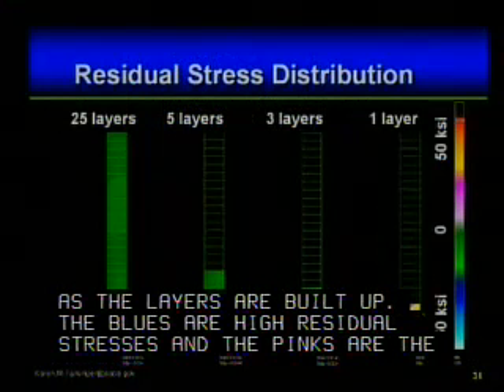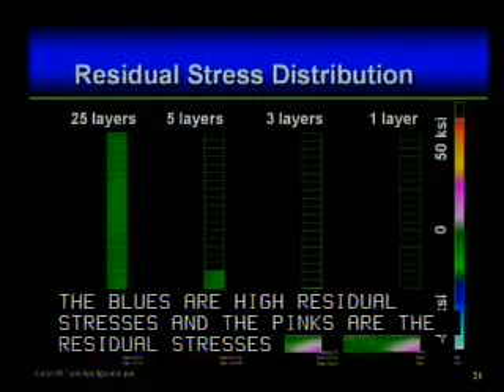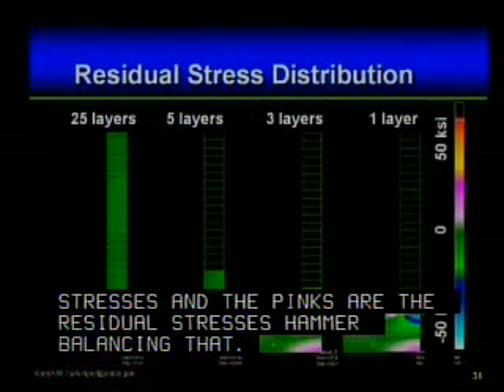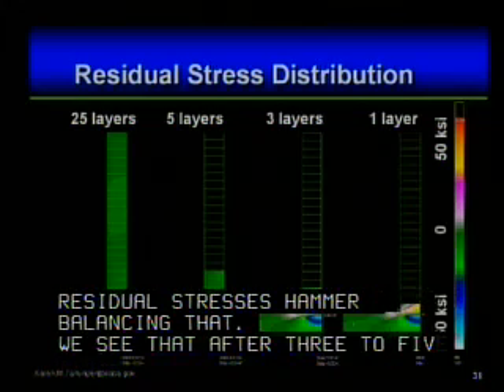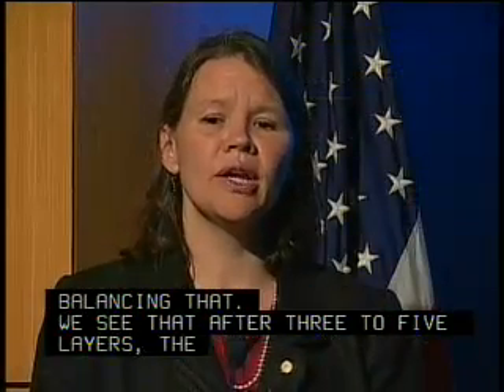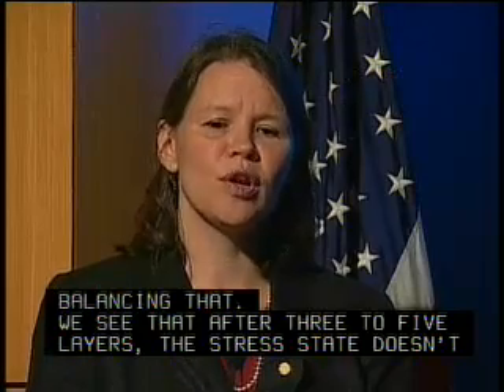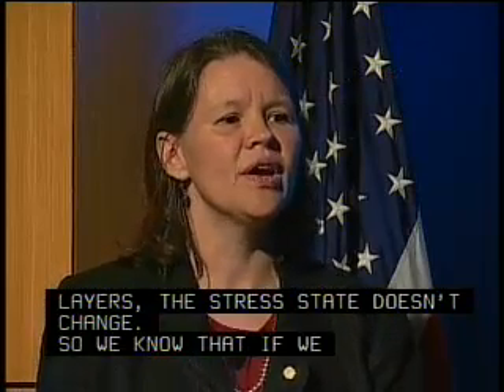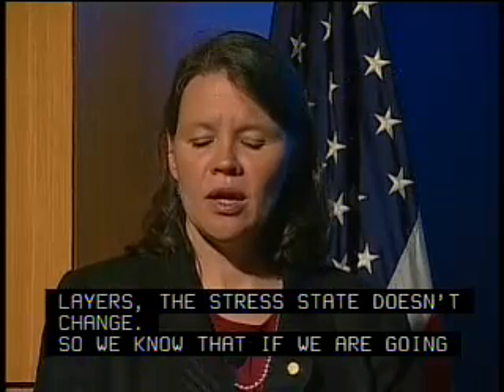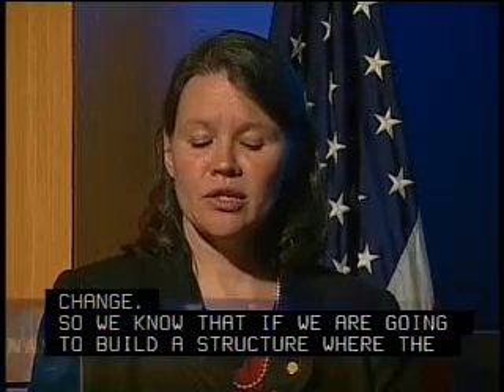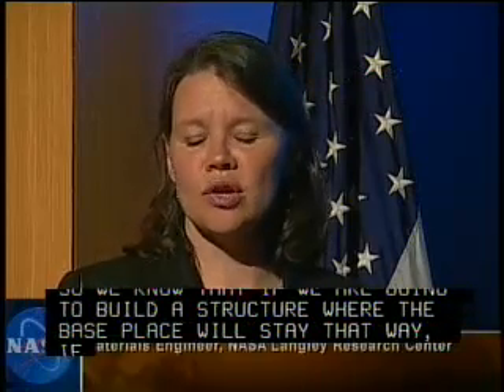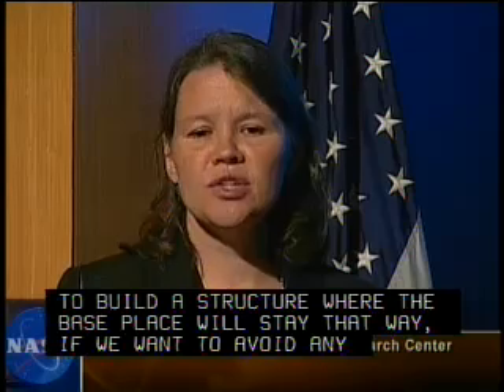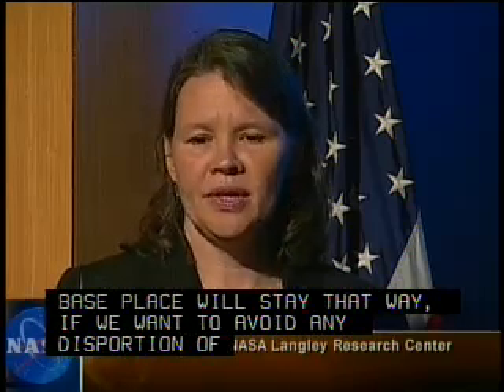But what we do see is that after about 3 to 5 layers, the stress state really doesn't change. And so we know that if we're going to build an integrated structure where the deposit is part of the base plate and it's going to stay that way, if we want to avoid or minimize the distortion and residual stress, we need to do it in the first couple of layers of build. Next slide, please.